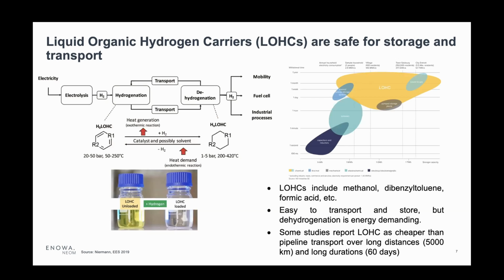Besides these carbon fiber vessels and underground storage, another way to transport hydrogen is using liquid organic hydrogen carriers. These are essentially chemicals and organic compounds that are able to store hydrogen. The general concept is shown in the top left. If you electrolyze water or make hydrogen from natural gas and capture the CO2, you can take that hydrogen and hydrogenate a molecule. Your simplest example is a molecule like toluene. Toluene is an aromatic, and if you add hydrogen to it, you will get methyl cyclohexane. So you hydrogenate. The hydrogenation process is exothermic. It releases heat. You can then move that methyl cyclohexane just like an oil or a liquid.